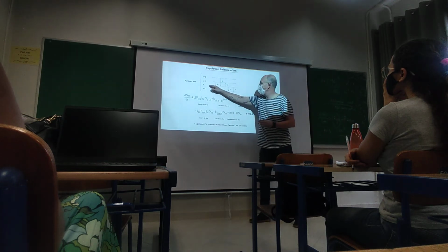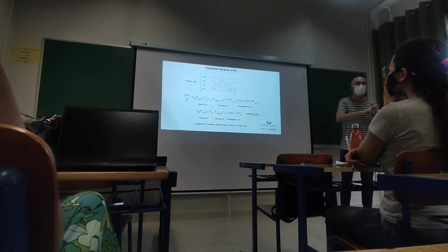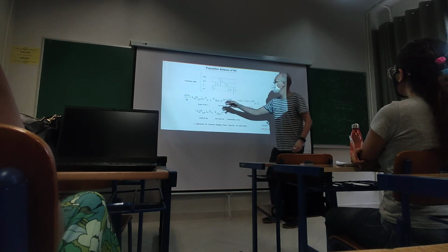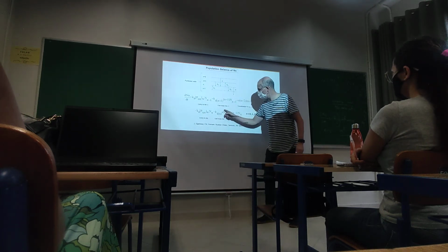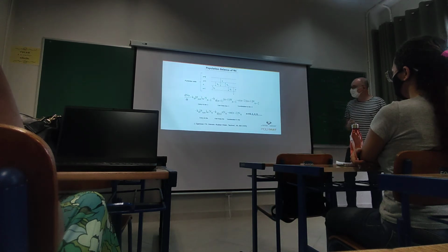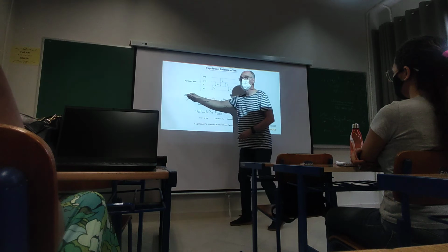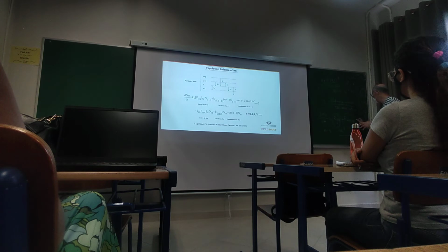Now, if in any particle with n radicals we have absorption, exit, or termination, these particles will disappear. So that's why we have negative terms for the absorption, desorption, and termination. Okay? Since these are balances for radicals, we can apply the pseudo-steady state assumption, and these differential equations become algebraic equations.